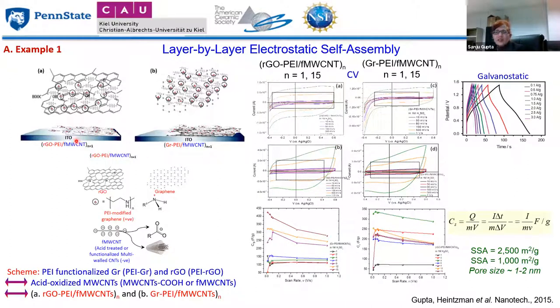And then we deposit them layer by layer, and we studied them. Basically one layer of graphene and one layer of multiwalled carbon nanotube, so this bilayer is one layer, so to speak. And then we studied them as a function of layers. The property we measure is called cyclic voltammetry, and that's what you see in these graphs on the right-hand side. These are polarization curves, which are basically current versus voltage, where the voltage or bias is with respect to a certain reference electrode. The more rectangular looking, the better, because this is a classic supercapacitive response.